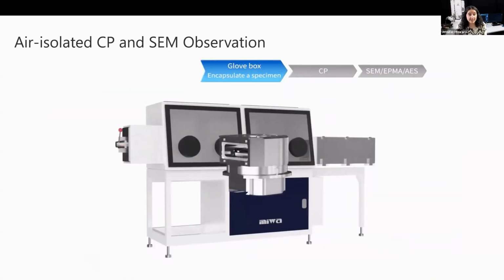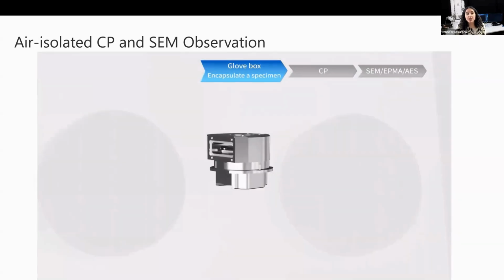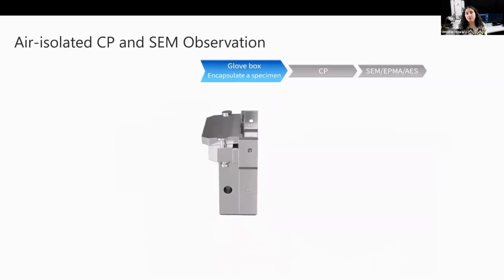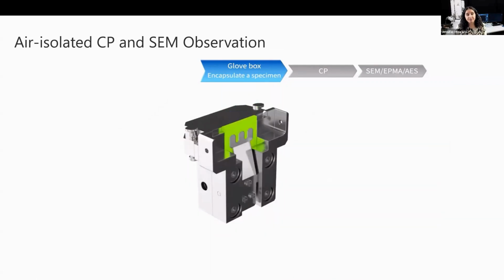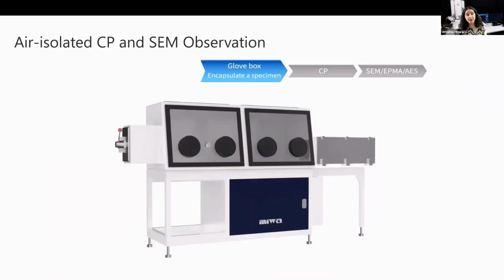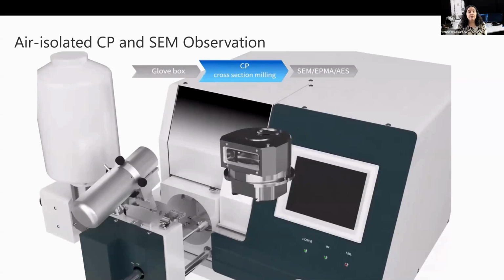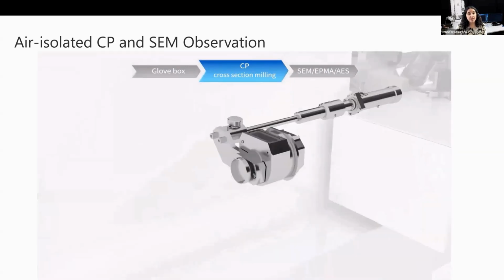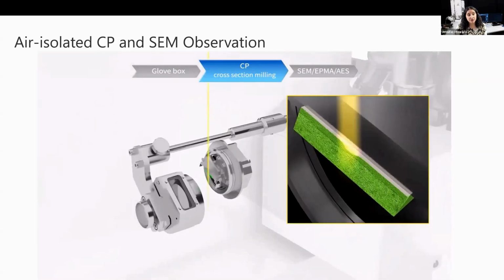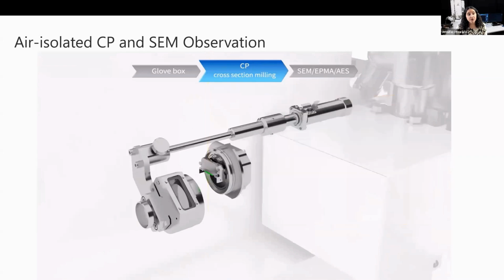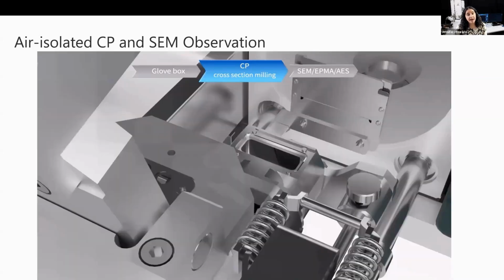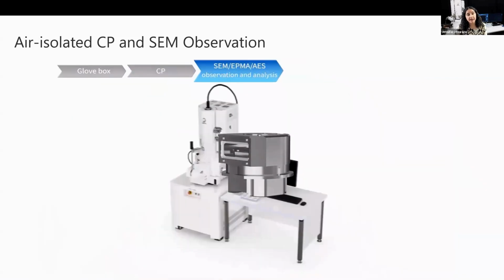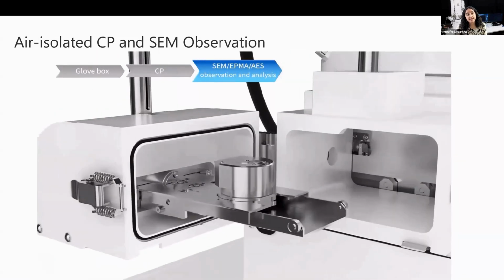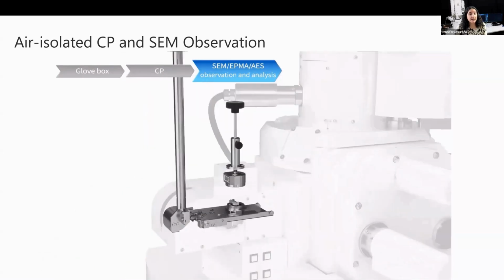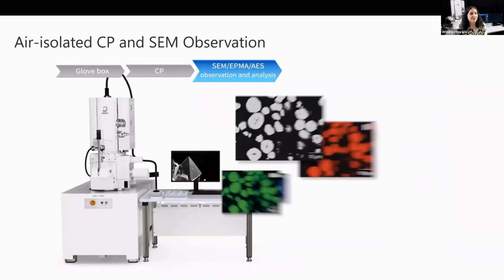This video will show JEOL's elegant solution for air-isolated applications, which can be completed on top-down samples or in one workflow, including JEOL's cross-section polisher. A sample can be prepared in the glove box and capped. Then the sample can be brought to the cross-section polisher, evacuated, and then uncapped and cross-sectioned. When the cross-section is complete, it can be recapped and brought directly to a JEOL SEM. The sample can be placed into the airlock and evacuated, and then uncapped before loading the sample into the chamber.